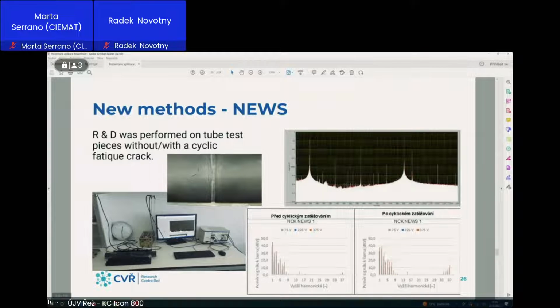During our research and development, we manufactured special half-tube specimens and performed measurements without and with a cyclic fatigue crack. Then we developed what we call a spectrogram. From the spectra we take all frequencies which are multiplications of F1 and F2, but here we put amplitudes only from the F1 frequency, and we evaluated that if there is a crack, then we can see it in multiples from 33 to 37, and that's how we can detect cracks.